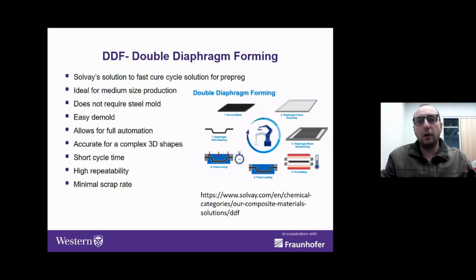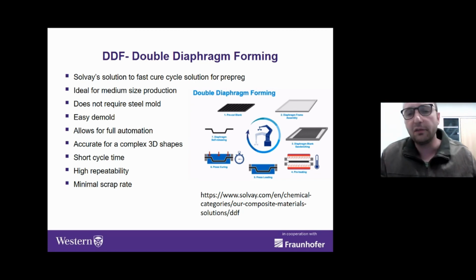Next process which we are looking for automation is Solvay's DDF, which stands for double diaphragm forming. That's basically Solvay's solution for pre-preg molding for medium size application in a fast cure cycle. The way the process works is you have a preform, you close it in a frame in between films, then it's heated to heat up the film and the preform, moved to the press, closed in the press, molded, press opens up, and the part is being removed.